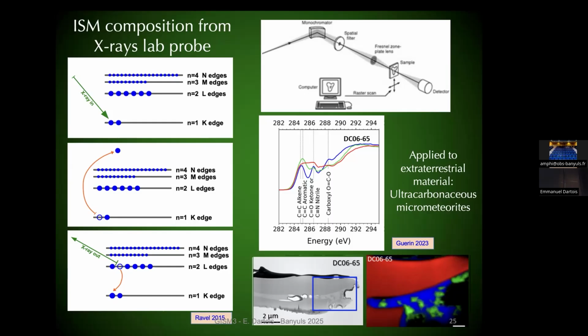So here is an example applied in the lab to extraterrestrial material. Here we are at the edge of the carbon atom energies, so an internal electron of a carbon atom. And you see that the position of the absorption will strongly depend on how this carbon atom is linked to the next elements. And so if you analyze these different substructures here, you can get information on the kind of bonds you have in the system. And if you can image this, so this is a micrometeorite focused ion beam cross section, you can even determine the different compositions in your system.